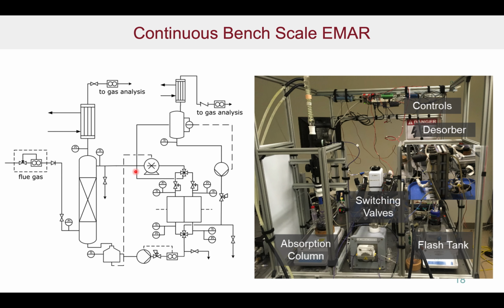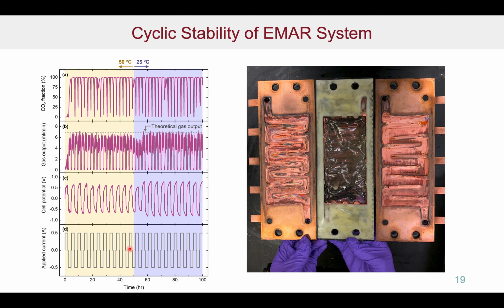This is actually a process we've done. We spent a fair amount of time looking at it, and we have a bench scale unit that's been operating effectively for many hundreds of hours on and off. And this shows the overall unit. That's the electrochemical cell we have. It's about 10 centimeters by 20 centimeters in size. We've got all sorts of other things here. We've got the absorption column, we have switching valves and things like that. And this has been used rather effectively over many cycles. This is 100 hours of continuous operation.